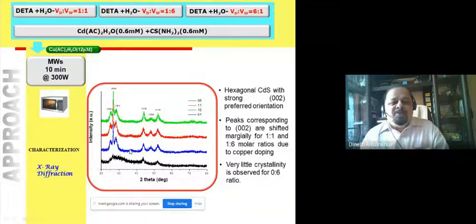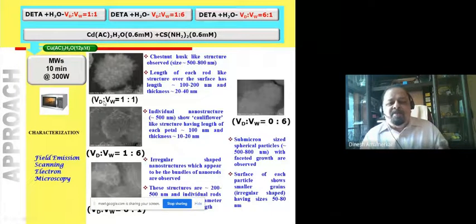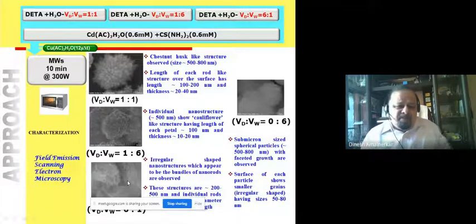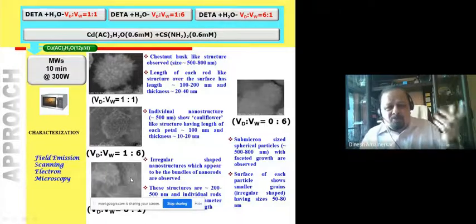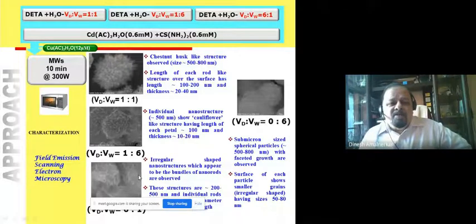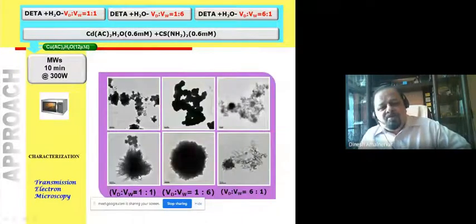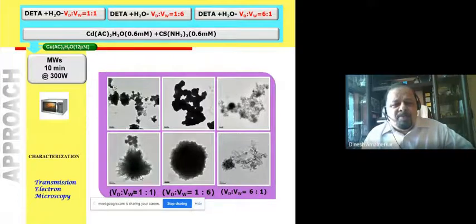Again, in this case also, we have seen this 002 preferred orientation of the hexagonal structure, and we get, in fact, much better morphology. This is chestnut husk morphology, and this is a cauliflower kind of morphology. In this case also, we could not find just spherical nanoparticles, but all the time, because of the 002 preferred orientation of the material, we could find the hierarchical nanostructures. TEM, somehow FETEM results are not so good, so I will skip that.